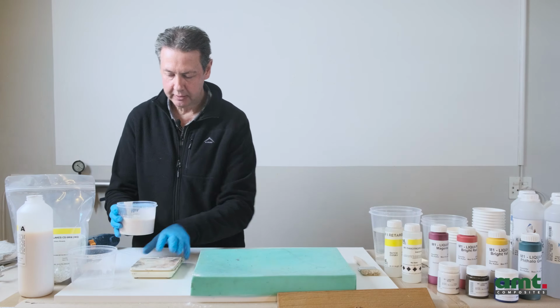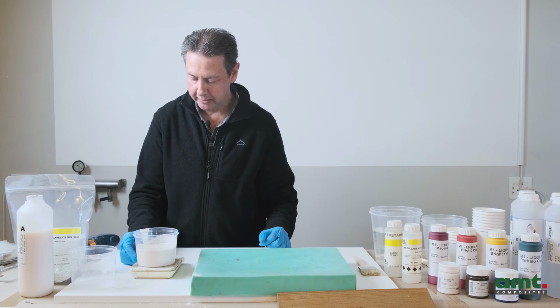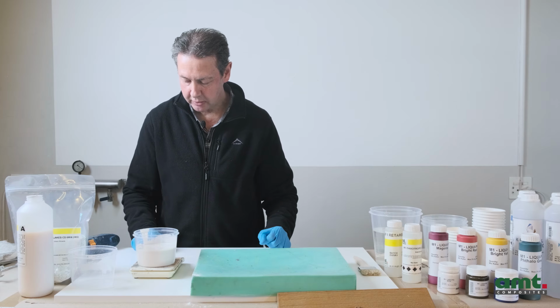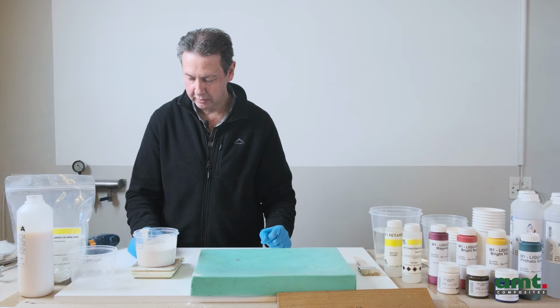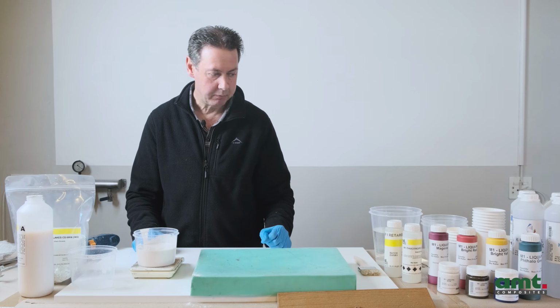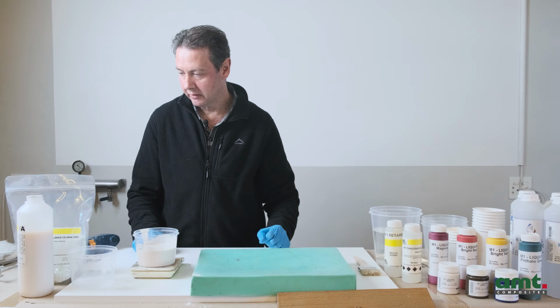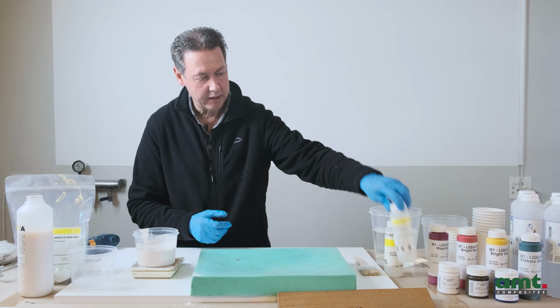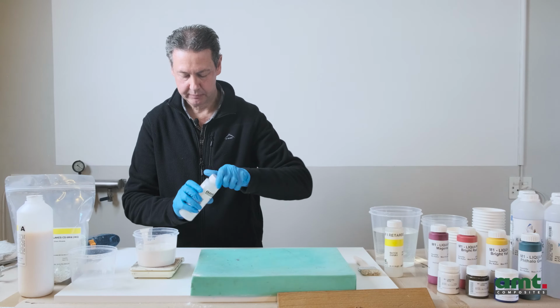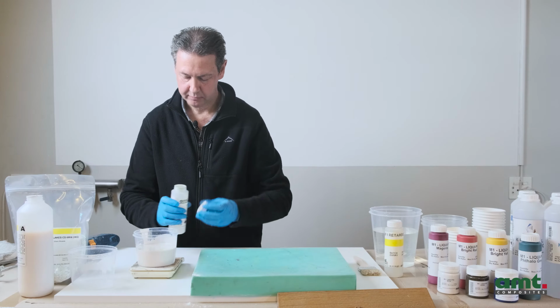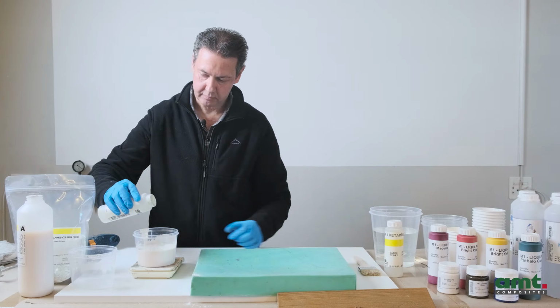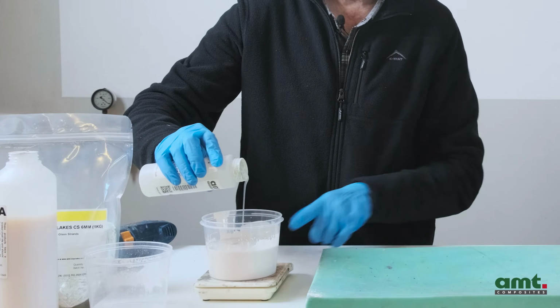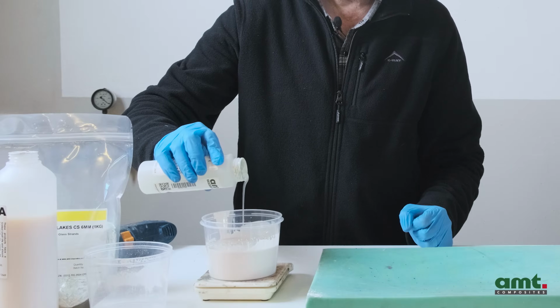Right, so now we're going to add the Thixer. So we add the Thixer to the total weight here. So we did 200 grams and 400 grams, so we've got a total weight of 600 grams here. So 2% of 600 is 12 grams. So we can go to a maximum of 12 grams of our M1 Thixer. So I can measure that 12 grams out nicely here.